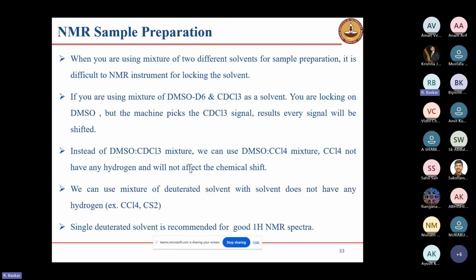When you are using a mixture of two different solvents for sample preparation, it is difficult for the NMR instrument to lock the solvent. If you are using a mixture of DMSO D6 and CDCl3 as a solvent, you are locking on DMSO, but the machine picks the CDCl3 signal. As a result, every signal will be shifted into the DMSO range. Instead of a DMSO CDCl3 mixture, we can use DMSO CCl4, because CCl4 does not contain any deuterium or any hydrogen. So the shift will not happen. So we can easily use this kind of mixture.